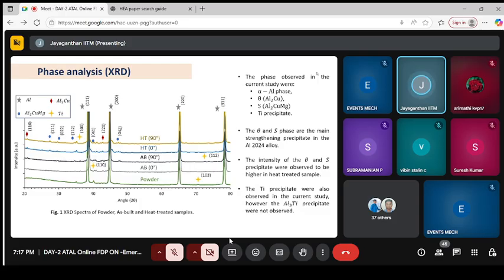What we want to highlight is that to get very good static and dynamic properties of this titanium added aluminum 2024 alloy, we are seeing the role of alloying elements such as copper and magnesium. Theta phase and the S phase are the main strengthening precipitates in aluminum 2024 alloy. Again, why should I care about composition? Why should I care about microstructure? Properties of the material are dictated by what kind of phase and what kind of precipitate they tend to form. Precipitate plays a major role.